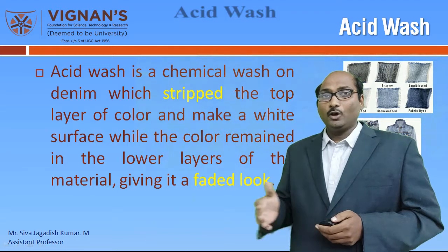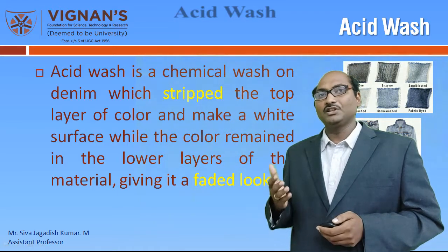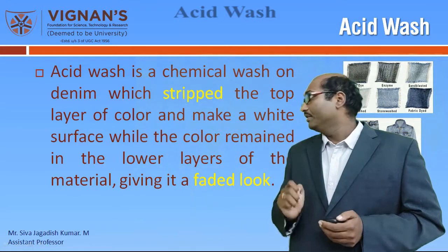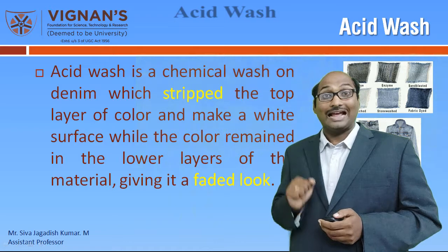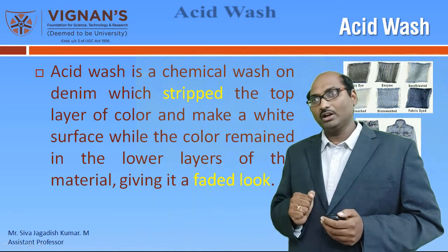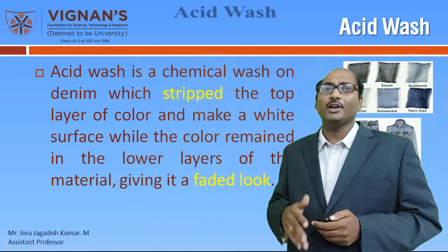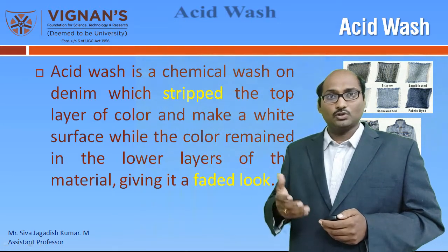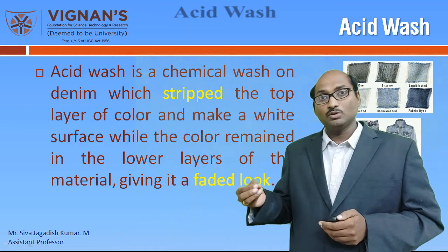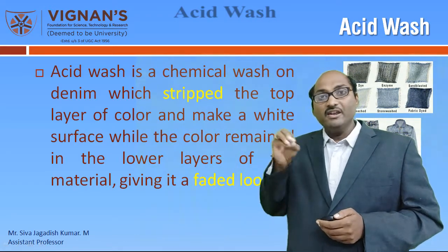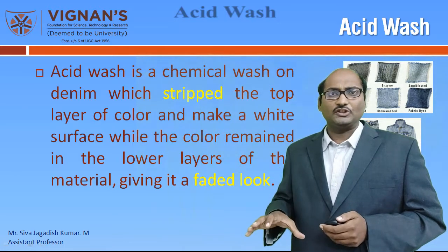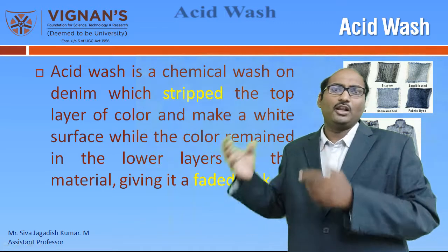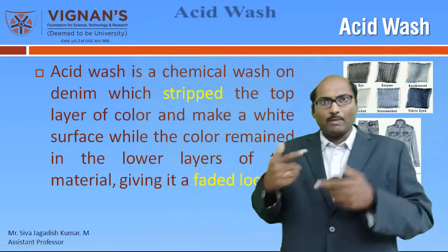The lower layer colors will be marginally removed and sometimes it may remain as it is, and it gives a faded look. Understood? Sometimes in acid wash we may not use water also. The same stones which we use in stone washing will be impregnated and immersed in the strong bleaching agent, and then these stones will be rolled along with the denim garments and tumbling will happen.